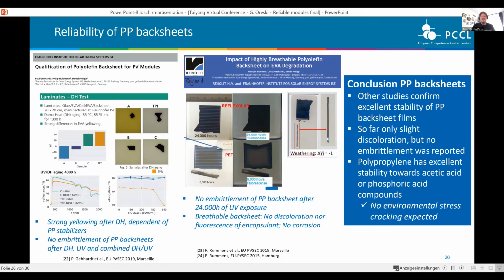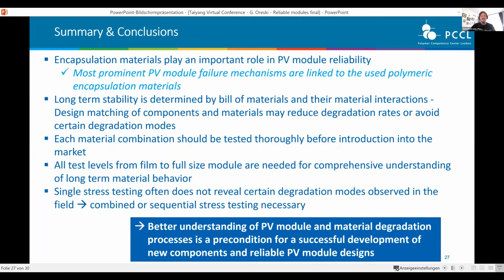And additionally, when we use it with EVA, and that's the big difference to polyamide, we have an excellent stability towards acetic acid. So we don't expect environmental stress cracking with this material. To summarize, I think we all know encapsulation materials, backsheets and encapsulants, play an important role in PV module reliability because most of the prominent PV module failure mechanisms are linked to the polymers used. The long-term stability is determined by which kind of material you choose and what kind of interaction they have. And when you do a proper design matching or check the compatibility, you may certainly reduce degradation rates or avoid certain degradation modes at all.